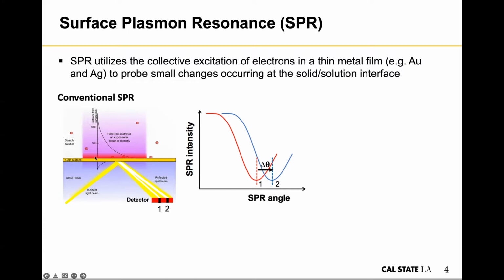Here I'm showing you a typical setup for a conventional SPR spectrometer, where you have a gold surface and incident light coming to the gold surface. At a specific angle, the light will be absorbed by the gold surface to generate a surface plasmon, and we call this angle the resonance angle. When you have changes ongoing on top of or near the gold surface, which is the sensor plane of SPR, the resonance angle will change. We call it an angle shift. Through the detector, you will see that the resonance angle moves from 1 to 2, and this angle shift is used to monitor any molecular interaction reactions at the sensor. So this is how a conventional SPR works.